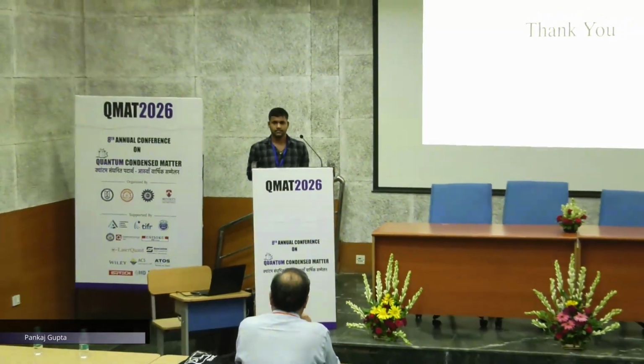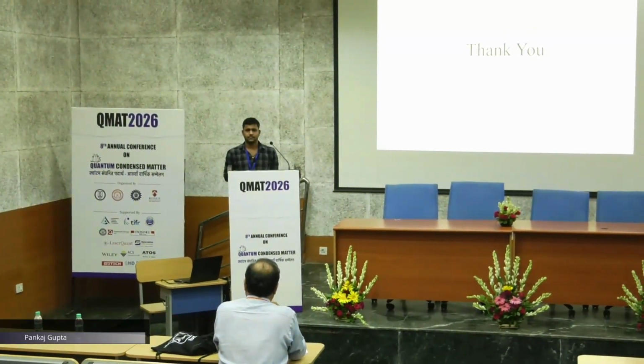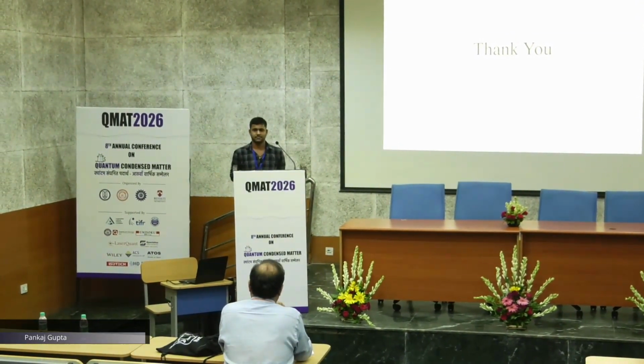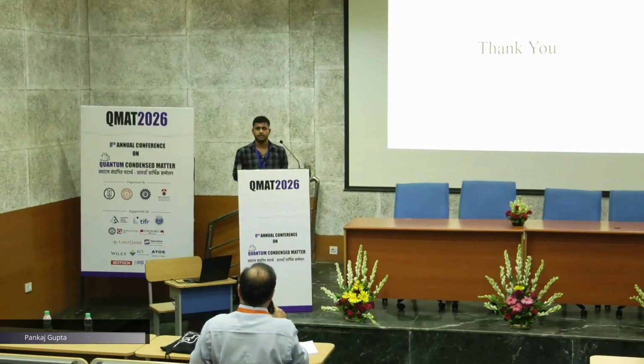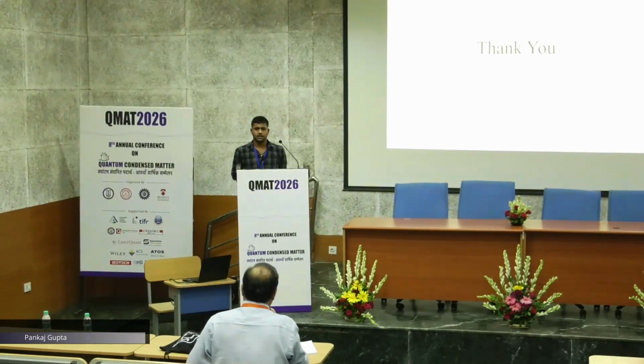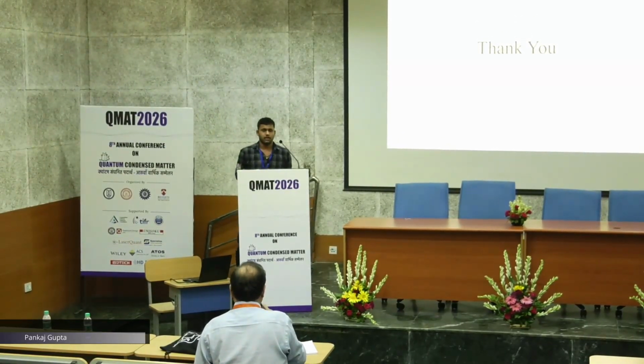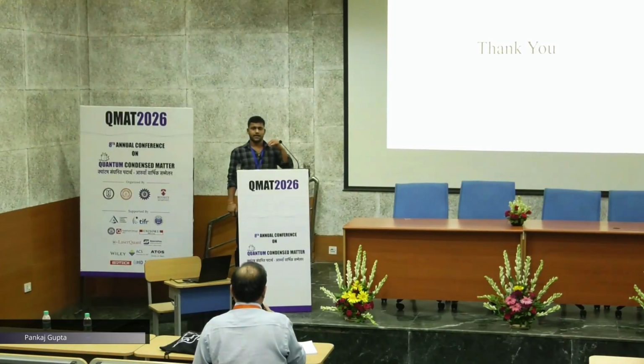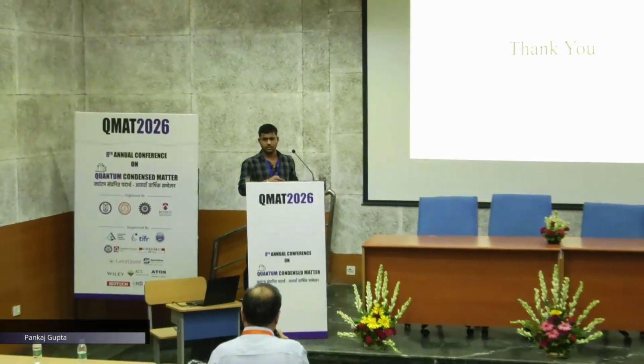Questions? The electronic contribution to thermal conductivity that you calculate theoretically from Wiedemann-Franz. Correct, sir. And which is the larger contribution, electrons or phonons? Phonon contribution is very low. Electronic contribution is very high, because you can see the electrical contribution is very high. But due to the disorder, the phonon contribution is very, very low, because phonons are getting scattered more and more.